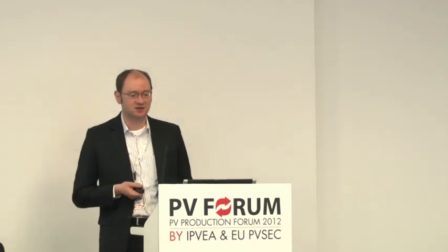One potential step change to the industry is the change from P-type to N-type wafers, but this poses some challenges for supply chains for both wafers and materials. N-type wafers prevent the degradation of minority carrier lifetime, since there is no boron present in the N-type wafers, and boron-oxygen complexes are known to reduce the lifetime of minority carriers. So higher efficiencies are possible.